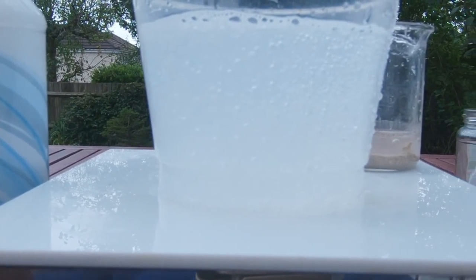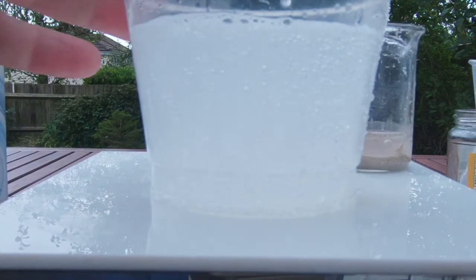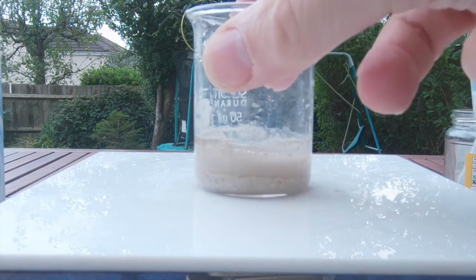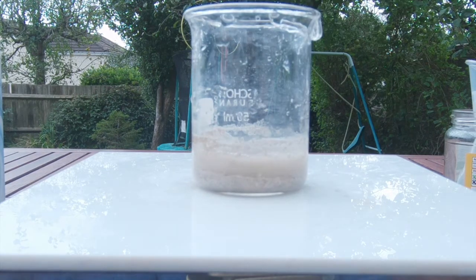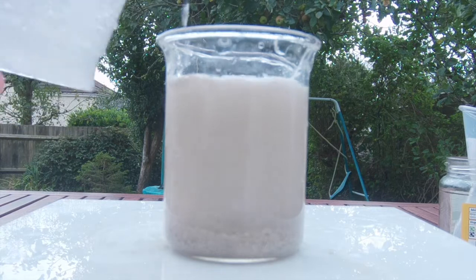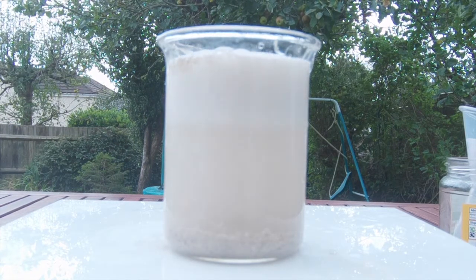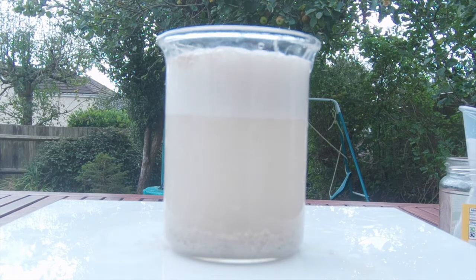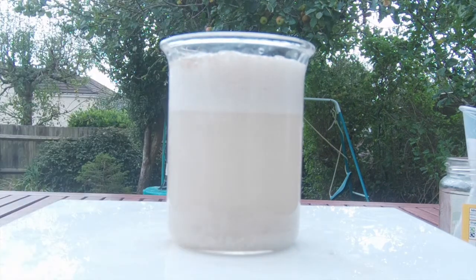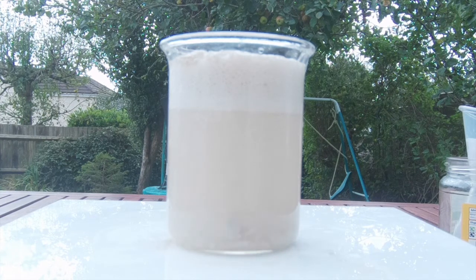So I'm going to put my rock powder with the magnetic stirrer on the plate and add the special chemical. The fabric softener is attaching itself to these micas and making them super water-hating. But that's not enough for them to go to the surface on their own - they want to escape the water, but gravity is pulling them down.